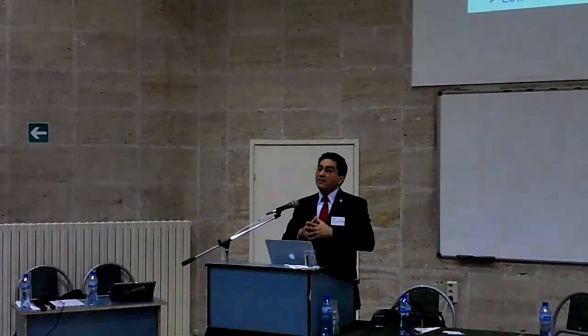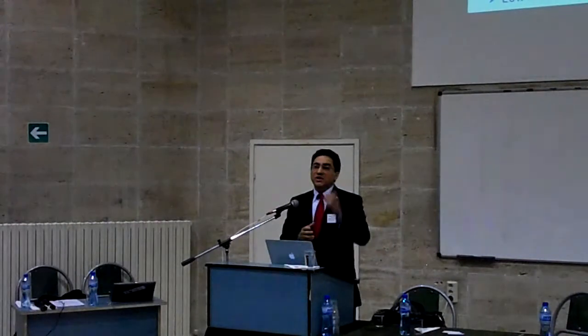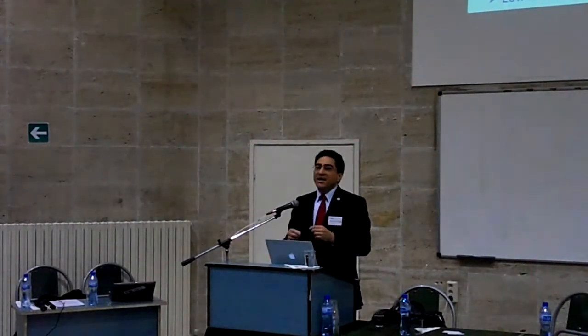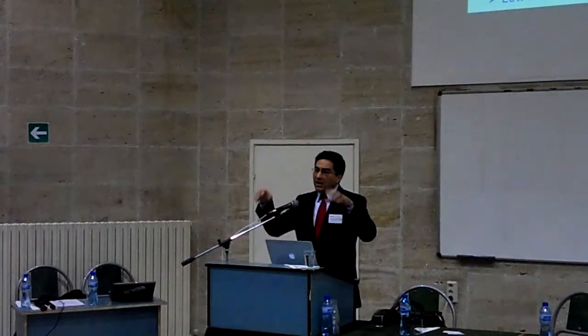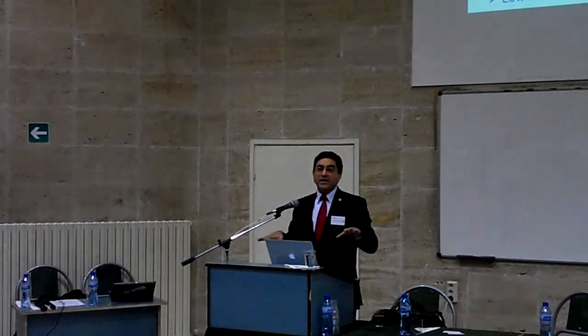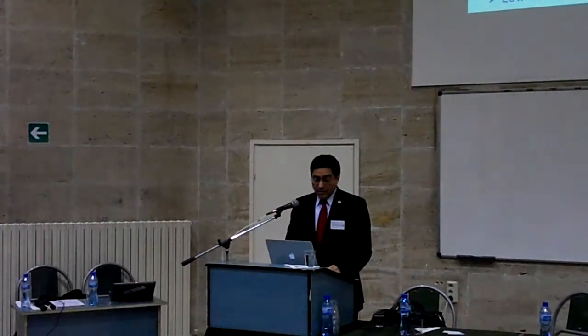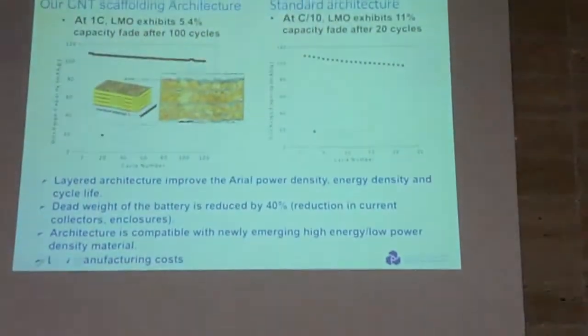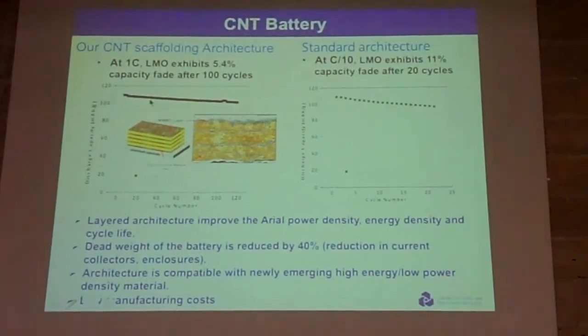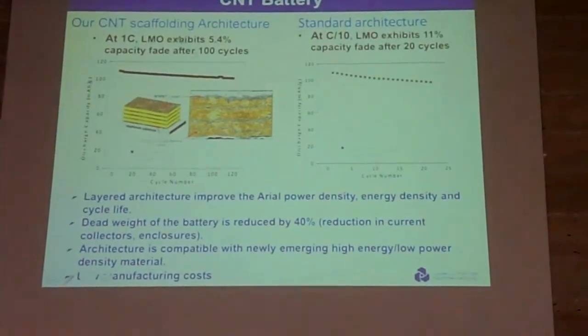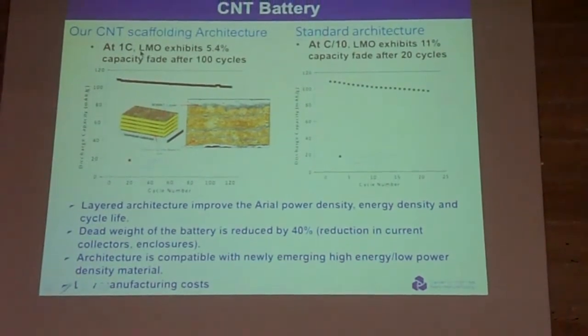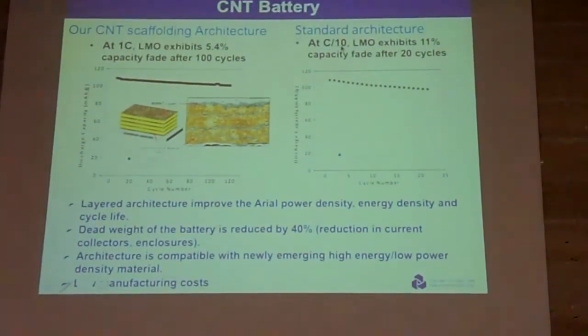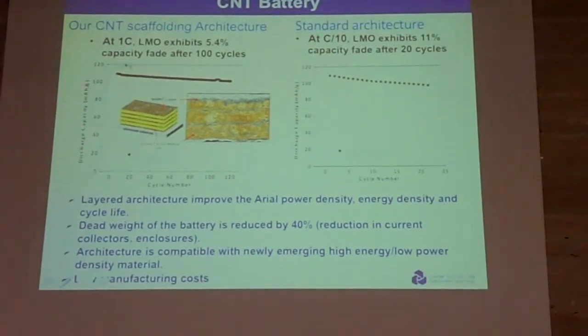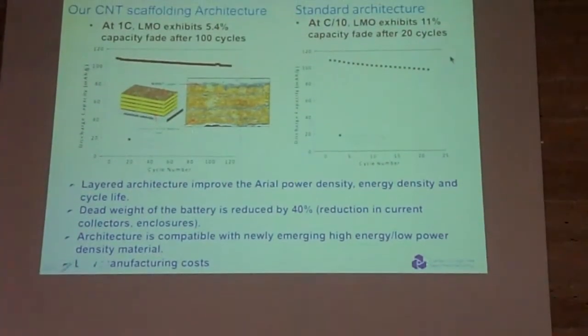So we said, okay, we want the battery to look like grapes. Each particle is connected to the body. We have nanotubes, and the particles are sitting on the nanotubes, and they're connected. They're always connected, so we always have access to them. You can see here, these are the active material, these are the nanotubes, for example. And we get much better results. This is charging at 1C, which means fully charged in 1 hour. This is a standard 10-hour charge, for example. You can see the fading is only 5%, whereas it is 11% at a much lower charge rate.